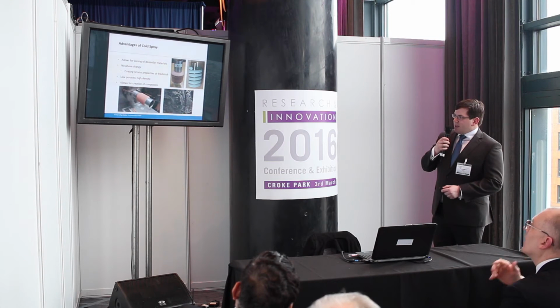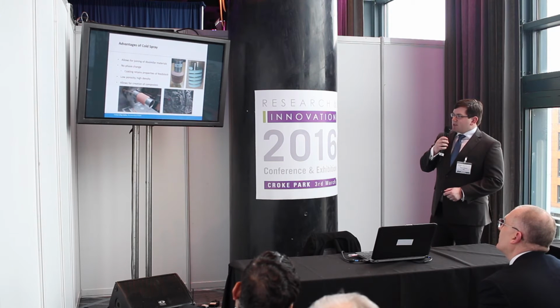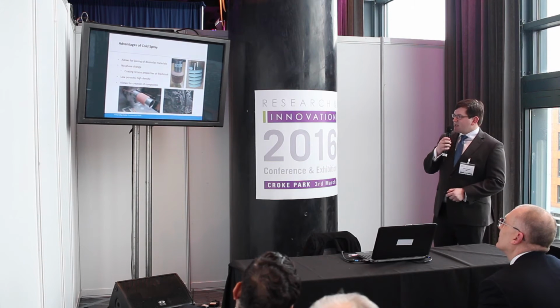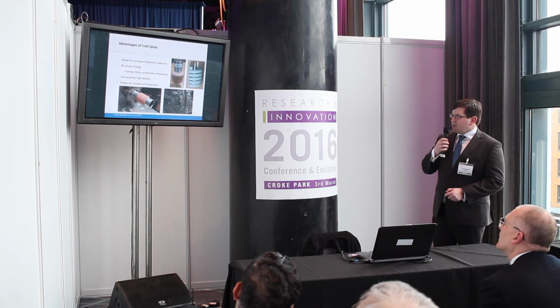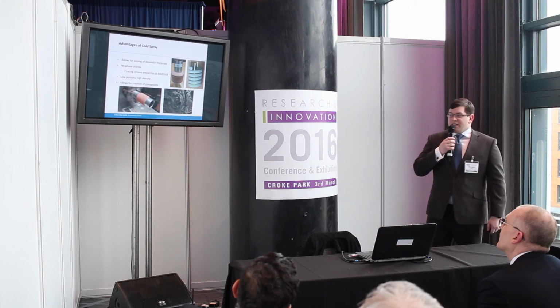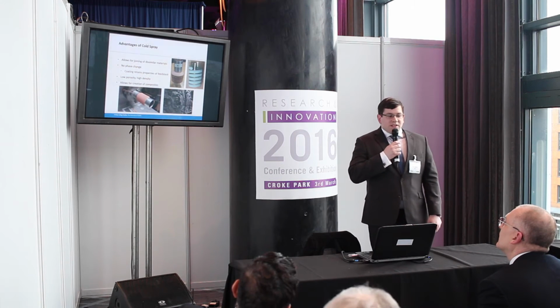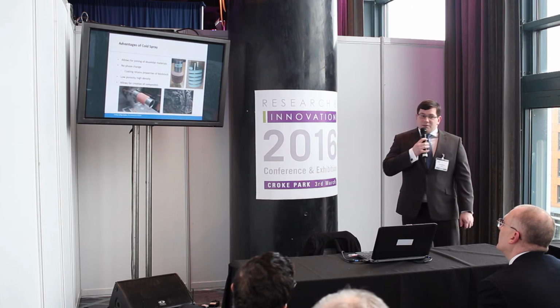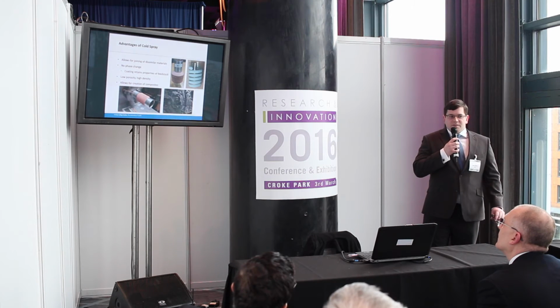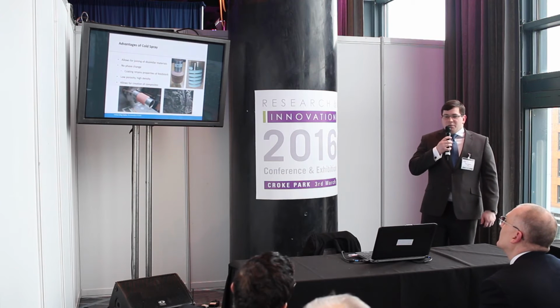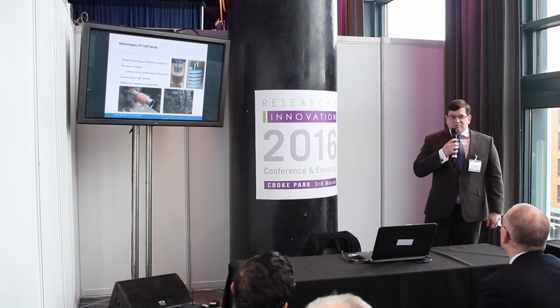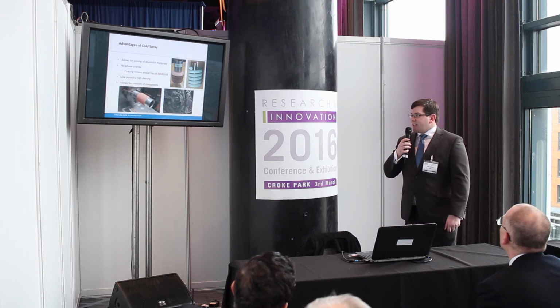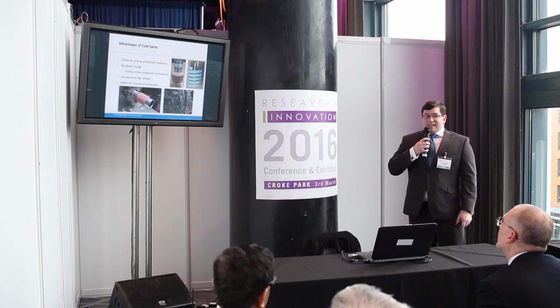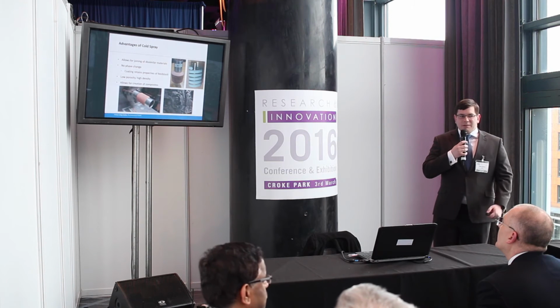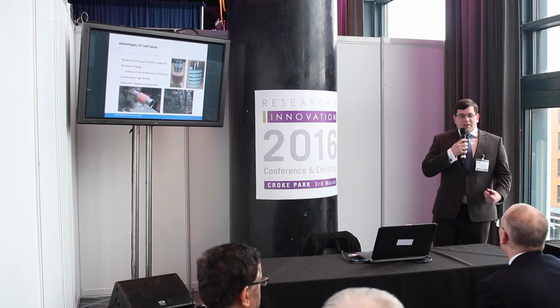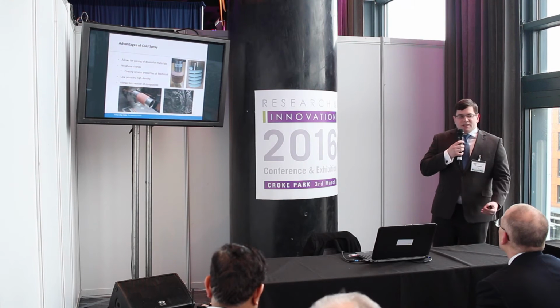Here we have another example of the copper onto aluminium, and talking about creation of composite materials. Bottom right here, not necessarily all that clear, but that is a diamond particle embedded within a copper nickel matrix. And we have shown in some of our tests that you can get a diamond fraction in the vicinity of 45 to 50% diamond by volume in a coating, which I actually don't think is possible or easily done with any other technique or approach. You can get very low porosities, very high densities if you get everything working right. And the key thing about cold spray is there is no phase change. Whatever you put in, you will get in your coating. There's no melting, no recrystallization.